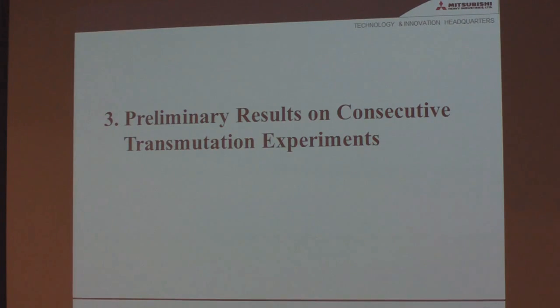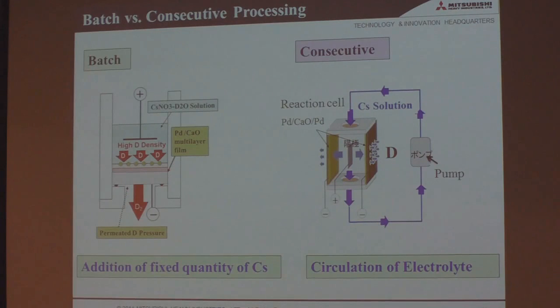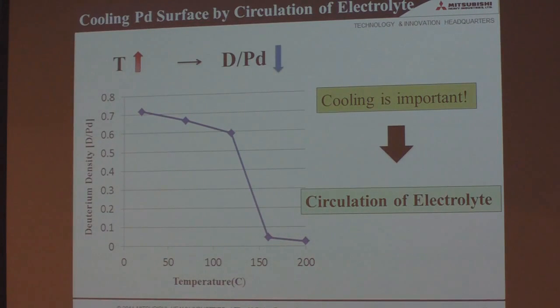Okay, so next point. I would like to present preliminary results on consecutive transmutation experiments. As I said, usually we put the cesium or other elements beforehand, a fixed quantity of cesium. Here, in this case, with circulation of electrolyte, we can provide much cesium on the surface. This is the electrolyte, and this is a palladium calcium multilayer thin film. So, consecutive transmutation, and we have another aim for this new experiment.